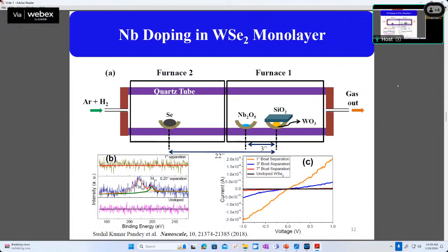Now, how to confirm whether this doping is done or not in a material system? For that, you have to do a process called X-ray photoelectron spectroscopy to check whether this material is actually present in the WSe2 lattice or not. So we found that this material is present. We found peaks related to that. So this indicates that the doping is done. Another way to confirm is to make two contacts and check the current voltage relation. If the current is increasing, this means the conductivity has changed. It confirms the doping. You can see here this separation, we varied this and we found that if the separation is 1 inch, we are getting good conductivity. So in this way, one can confirm the doping part.